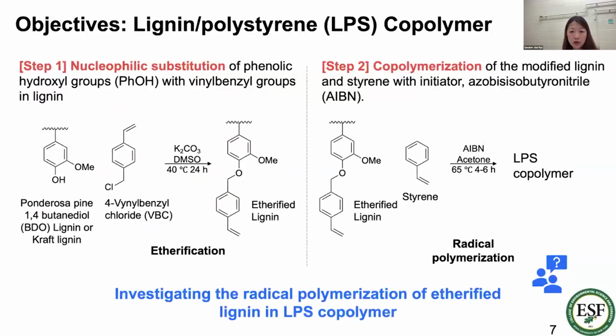In detail, there are two steps in this polymer process. Step 1 is the lignin modification. We use nucleophilic substitution of the phenolic hydroxyl group with the vinylbenzyl group in the lignin structure. To use the ponderosa pine-derived lignin resource, we selected 1,4-butanediol biomass pretreatment for the lignin production. We also compared industrial-level kraft lignin to see the difference between industrial lignin production and the BDO lignin properties.